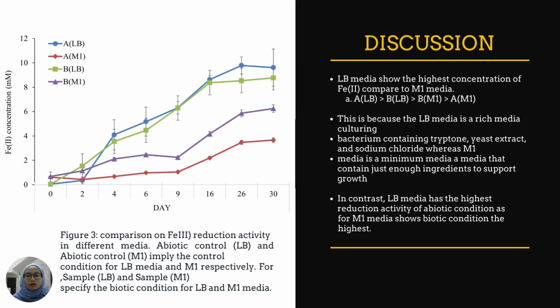Overall, based on figure 3, both abiotic and biotic conditions in LB media show the highest ferrous concentration compared to M1 media. These results suggest that LB media is a rich media for culturing bacterium containing tryptone, yeast extract, and sodium chloride for Shewanella growth with iron nail incubation, while M1 is a minimal media composed of only minimal ingredients to support Shewanella growth.